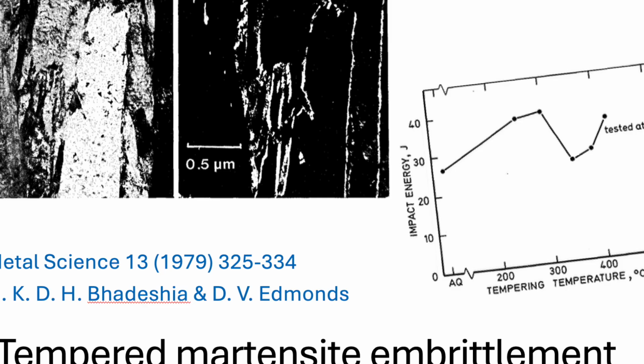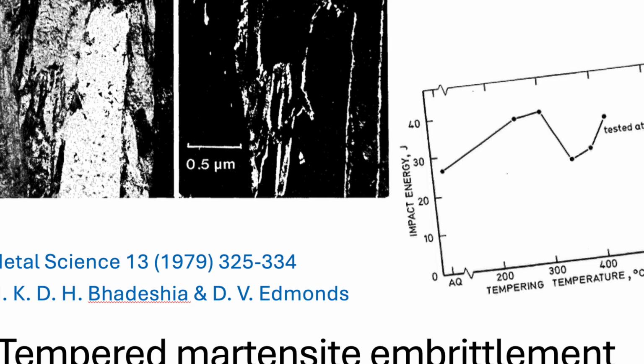Okay, let's start with a clear definition then. What is TME? What's the observable problem we're talking about? So TME is basically a sharp, very localized reduction in fracture toughness. It happens when you take these quenched low alloy steels and you temper them, typically in the range of about 300 to 500 degrees Celsius. And that's the weird part, right? You expect tempering to make it tougher. You do. You expect it to become tougher, maybe a bit stronger as you temper it. But in that specific temperature window, performance just falls off a cliff. The steel becomes surprisingly brittle.